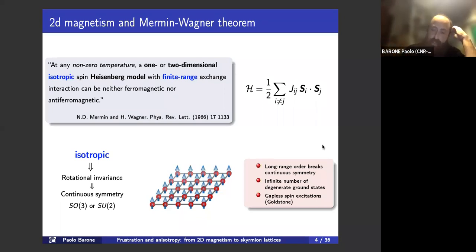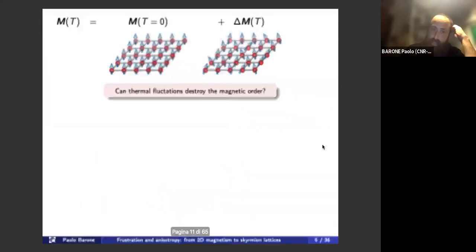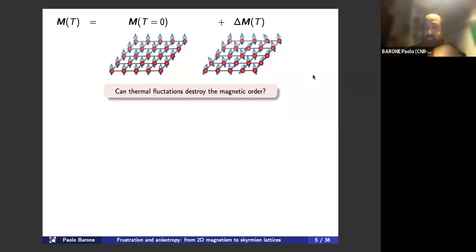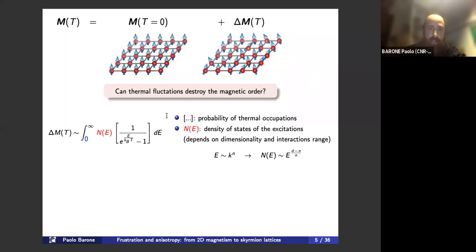Now, the physical content of the Mermin-Wagner theorem is this: if we assume that we have some finite magnetization at finite temperature, we can express it as the sum of the ground state magnetization and the effect of the thermal fluctuations of the system. We can ask ourselves whether these thermal fluctuations may be so strong that they can destroy the magnetic order. I'm not providing here the original proof of the Mermin-Wagner theorem, just enough to let you understand the point. We can write the contribution of the thermal fluctuations as an integral containing the density of states of the excitations of the system multiplied by the thermal occupation probability.